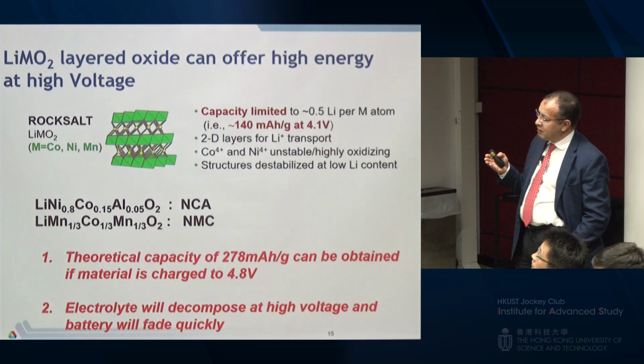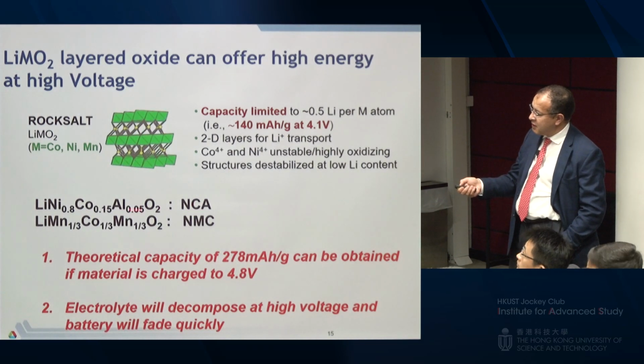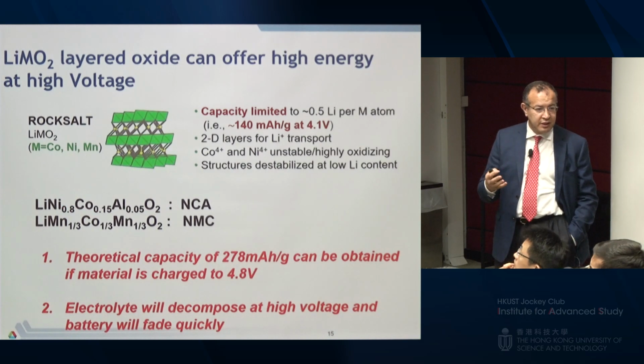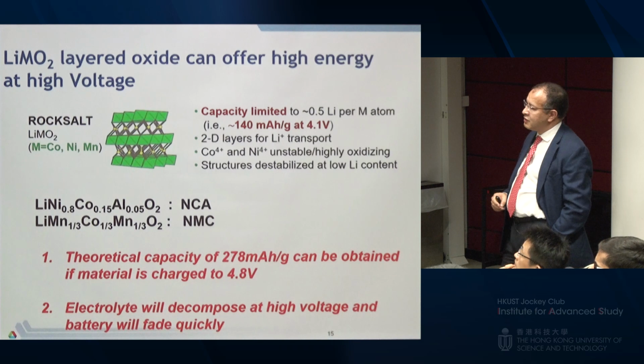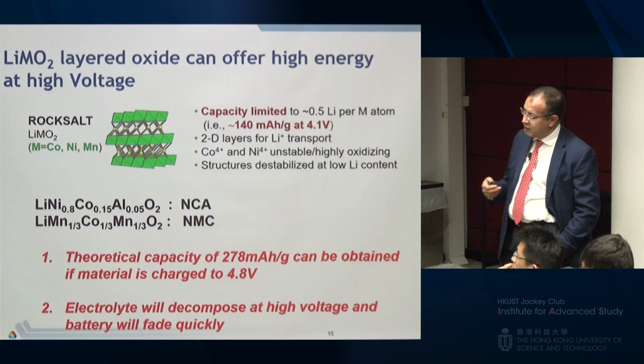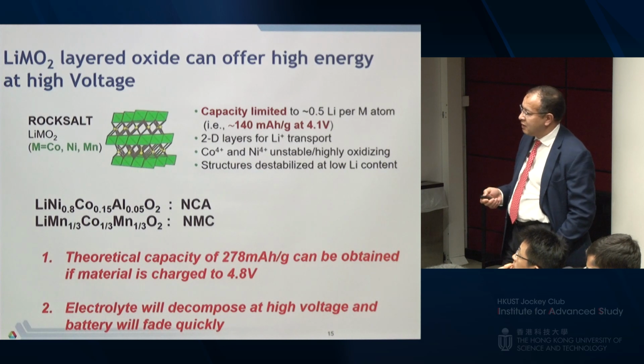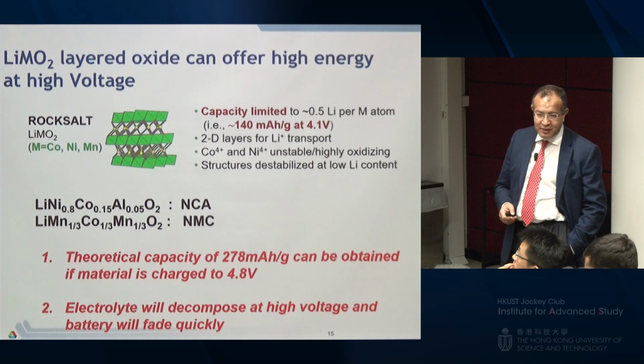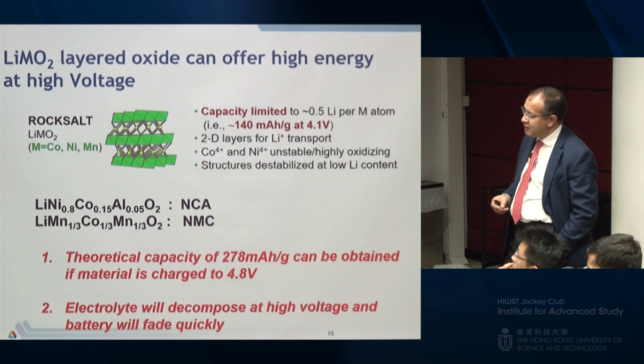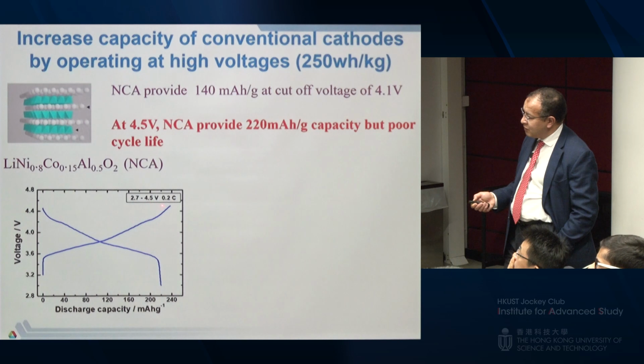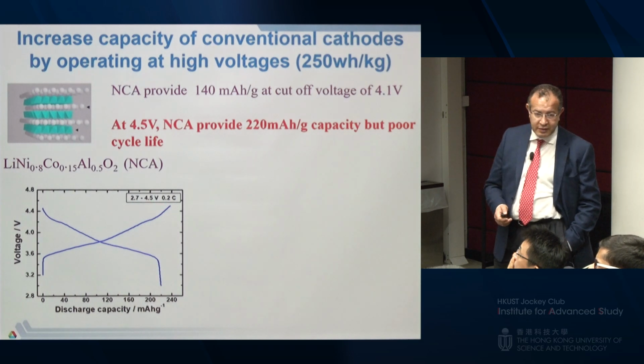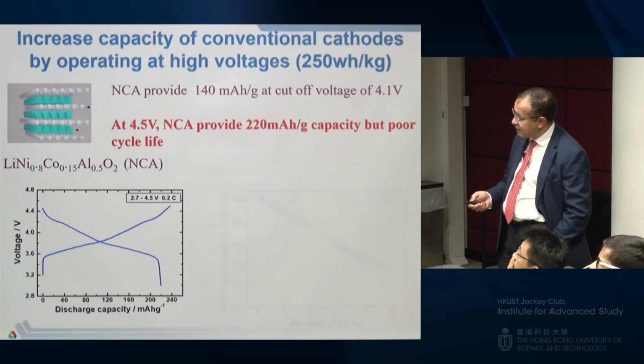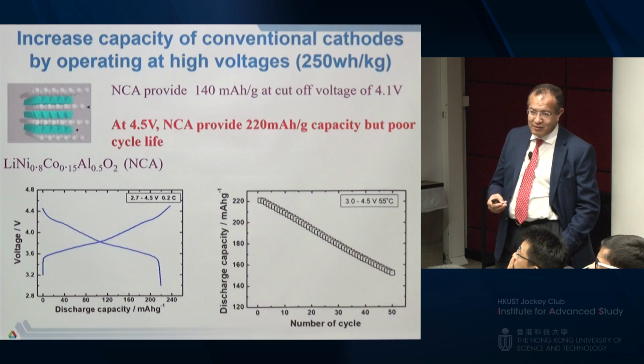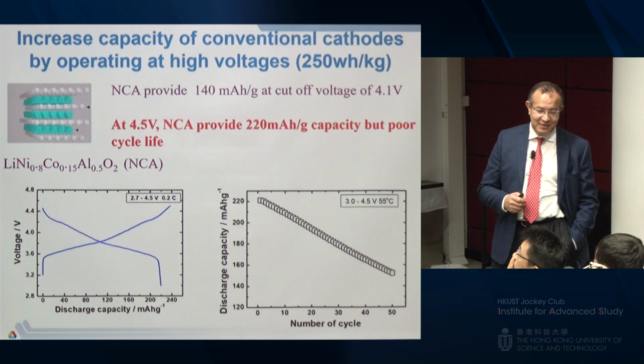Now, if you take, for example, the NCA, this is the Tesla technology. They use a very high concentration of nickel. When you charge this system at high voltage, let's say 4.2 volts, you can pull a lot of capacity out of this system. If you go higher in voltage, you can get almost close to the theoretical value, but the problem is at this level the material is very unstable, so it decomposes the electrolyte. Here is an example. If you charge to 4.5 volts, you get very large capacity, almost 220 milliampere-hours per gram. But then if you cycle it, it drops very quickly. So you get the energy, but you lose the cycle life, which is a problem.